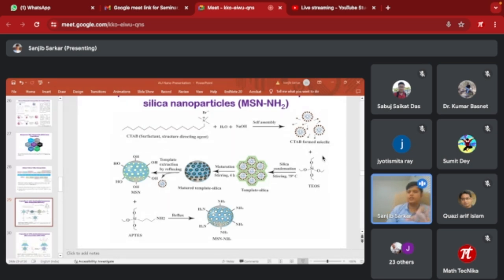So after formation of this nanoparticle, we loaded vitamin D or vitamin K in the nanoparticle pore. Here you can see this is the nanoparticle. These are the nanoparticle pores, and in the nanoparticle pores, we loaded the vitamin K or vitamin D, and then the pores of the nanoparticles are closed by dextran. This is a carbohydrate polymer.